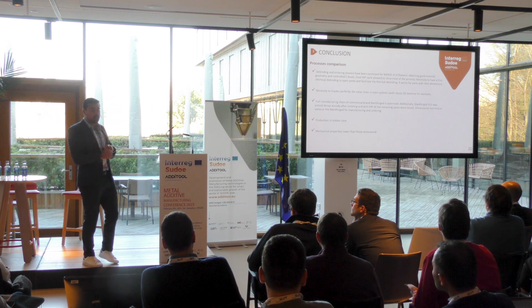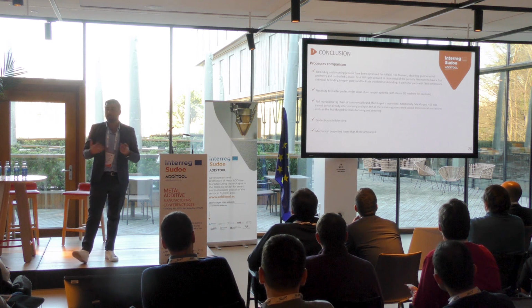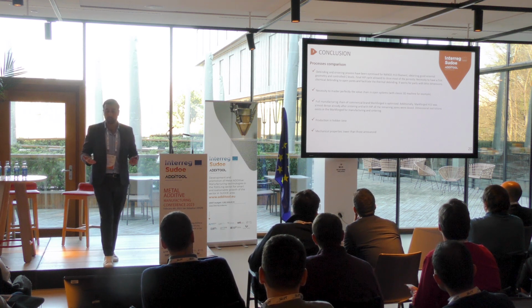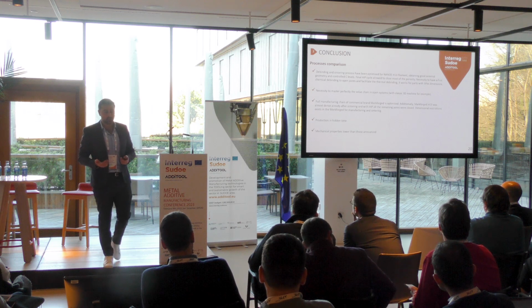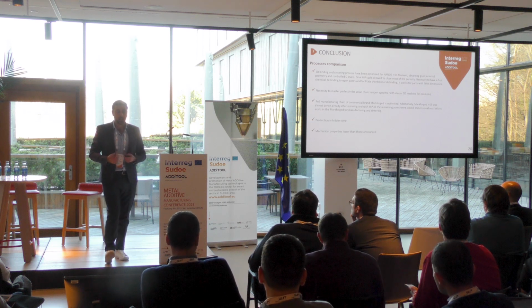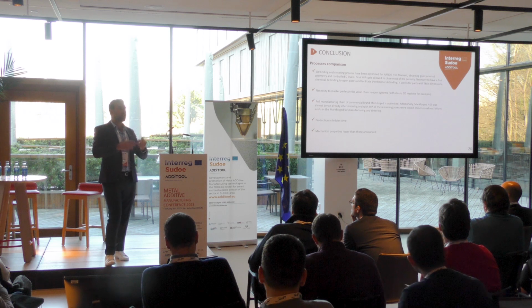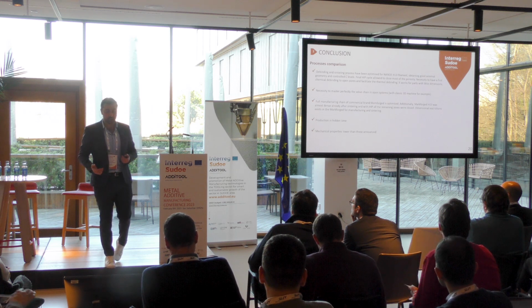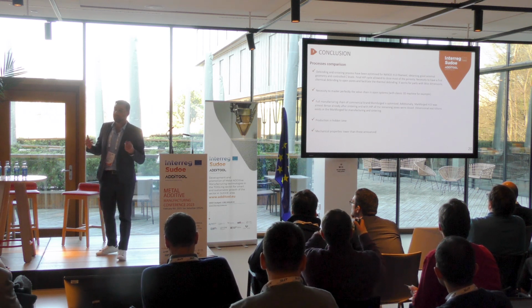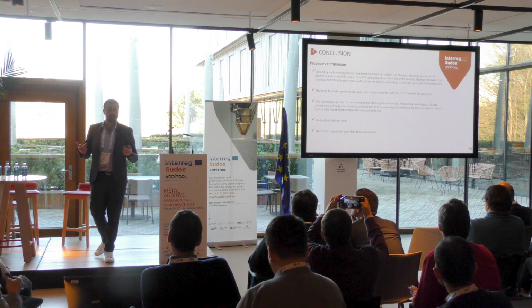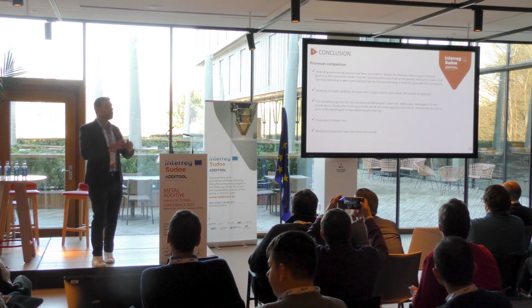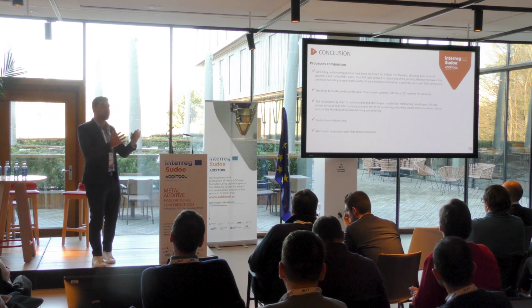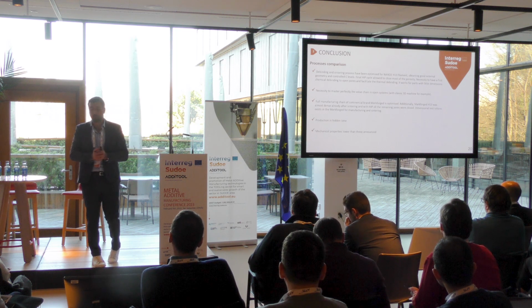The full manufacturing chain of commercial brand Markforged is already optimized, and there are good results on it. It's almost dense already after sintering, and with HIP we close the remaining porosities. But dimensional restrictions exist in the Markforged also, because you are married to the oven and to the sintering oven.